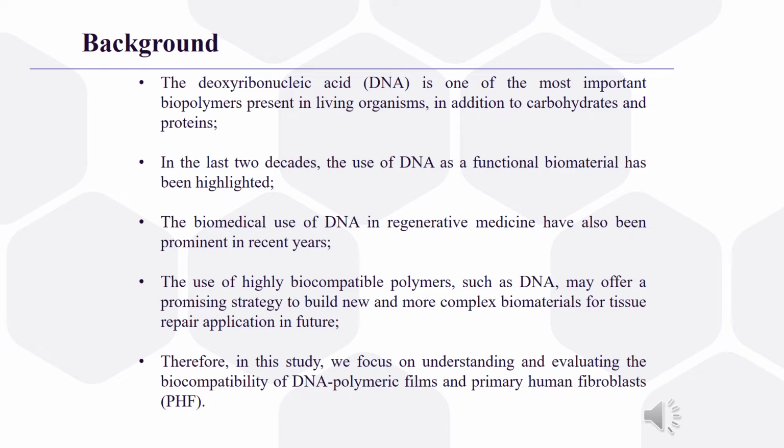This method involves dispersing a film formation solution on a support, usually a petri dish or glass, followed by slow dehydration, leading to a well-structured 3D material. Then the morphological structure of the DNA polymeric film was observed by SEM, scanning electron microscopy, elementary microanalysis, and atomic force microscopy.